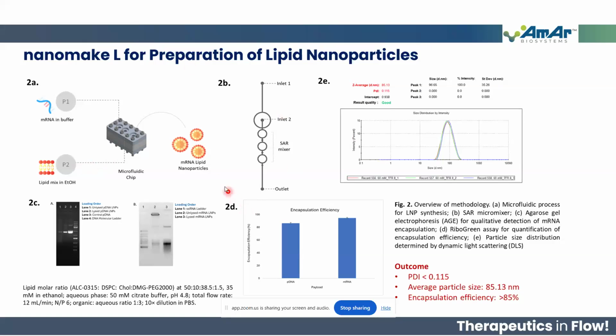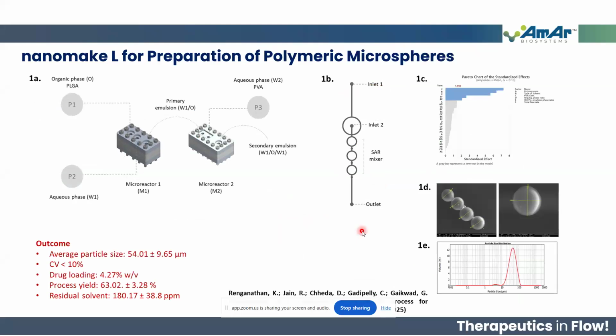And the geometry of our device is essentially a split and recombination type micromixer. And this design allows for increased residence time within the microfluidic chip, but it does not cause microchannel clogging in comparison to a herringbone shaped design. Now, we achieved a particle size of about 85 nanometer and an encapsulation efficiency of more than 85% for plasmid DNA and more than 90% for mRNA. Similarly, we have also optimized this system for preparation of polymeric microspheres. And here you can see we achieved a particle size of about 50 microns and a variation of less than 10% between each batch.